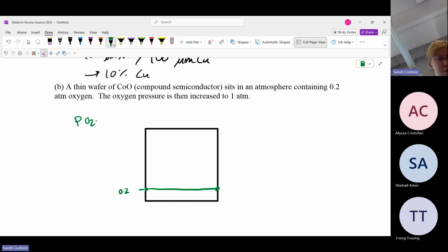So I'm going to call this PO2 ATM. But then we increase the oxygen pressure to 1 atmosphere. So what that's going to do is fix it on the outside at 1 atmosphere, 1.0. Because it's thin, and we assume that we're in an open container, this 1 atmosphere on the outside will not be changing. No matter how much diffuses in, the oxygen in the air isn't going to change in terms of pressure or in terms of concentration. And the cobalt from the semiconductor isn't going to be diffusing out into the air either, or not in any meaningful capacity. So we're going to fix this at 1 atmosphere, and what's going to happen is just slowly over time, this line is going to move up to meet that 1 atmosphere, because we're going to diffuse that oxygen in to be at the same relative concentration.